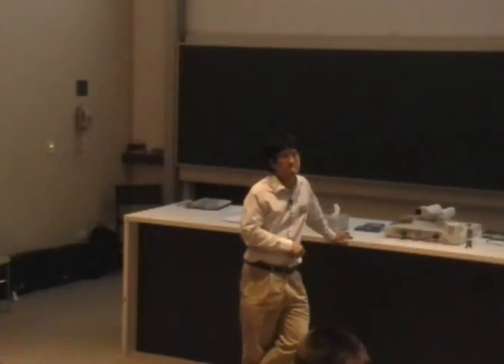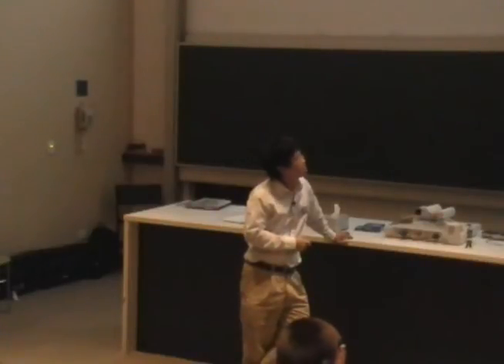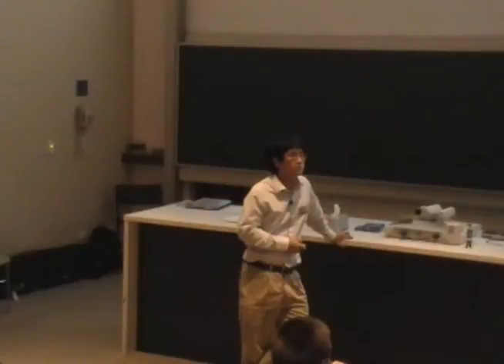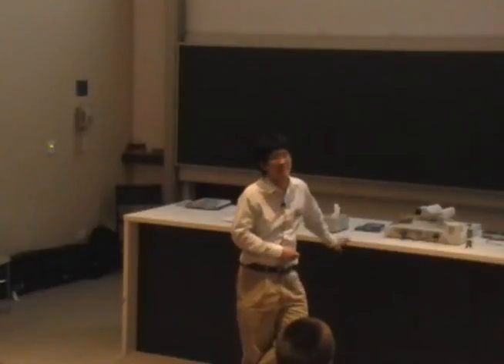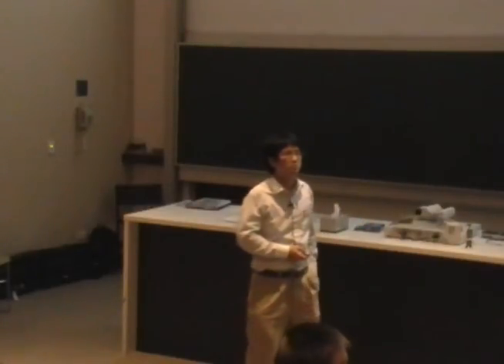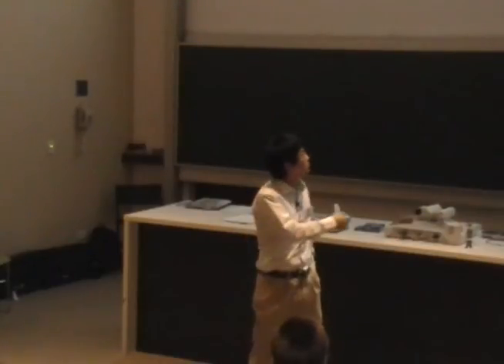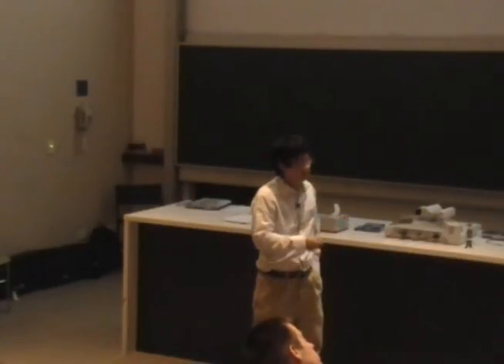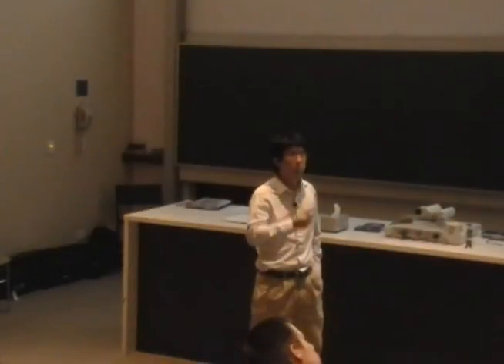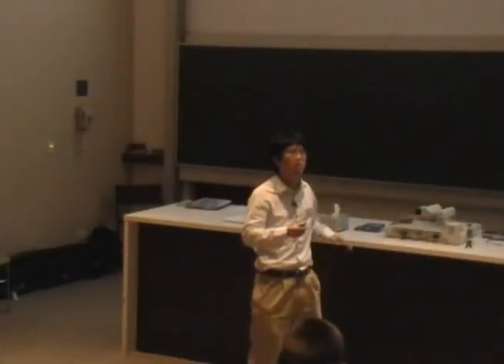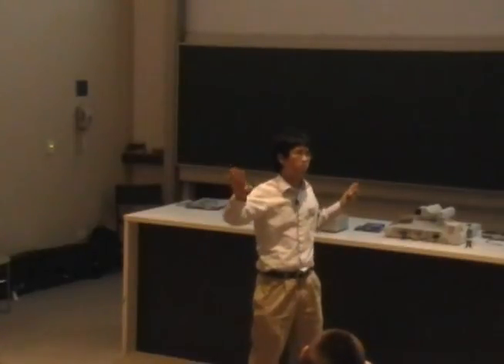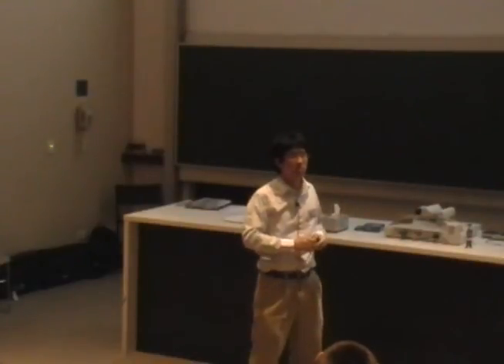Okay. Then my second question is for Kwan. You have PCBM rich on both sides of the mixed layer, so is there not an issue for hole drift? Oh yeah, it is an issue, but it's something we haven't been able to control. Obviously, it would require more fine-tuning to try and prevent that. Interestingly enough, I saw a slide from this group, and they see the same effect as well in their BHJ. The PCBM likes to pull up at the two interfaces, and I've been told that that's been submitted to a journal. I don't know which journal, but we'll see that soon.